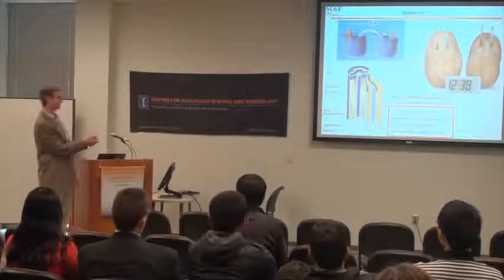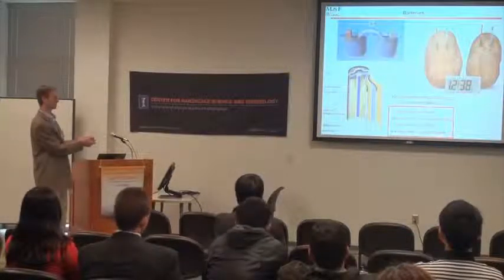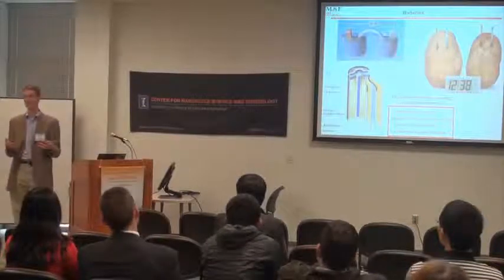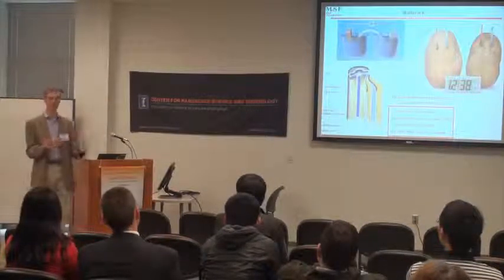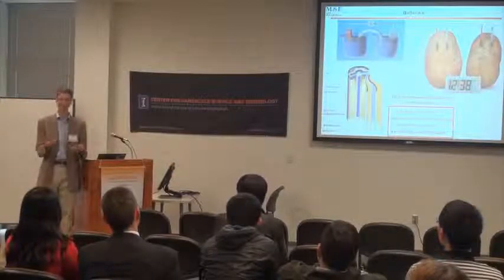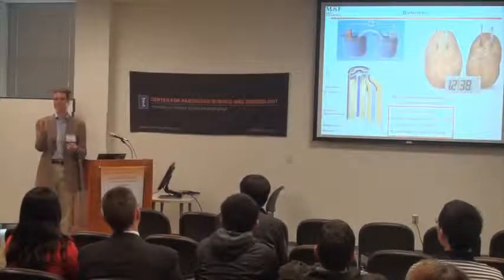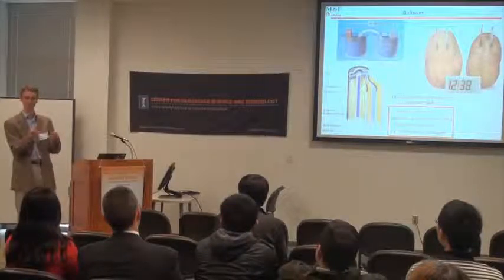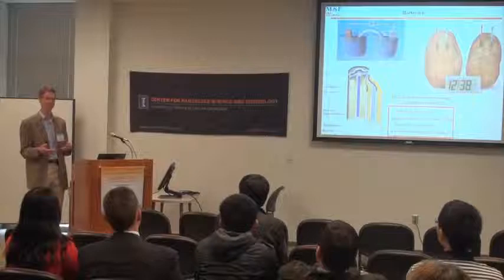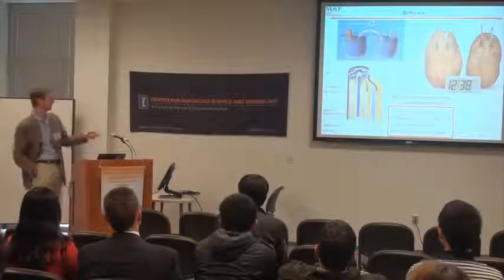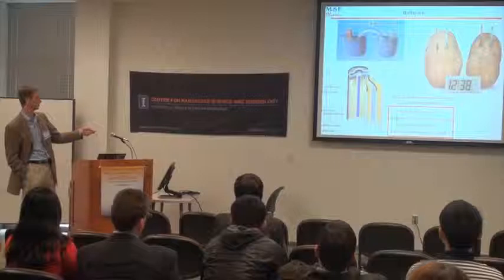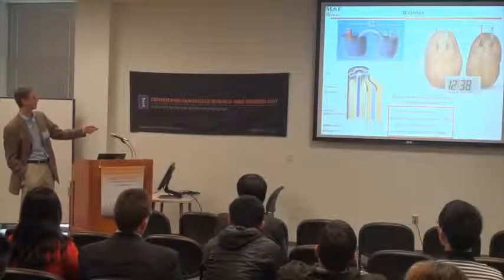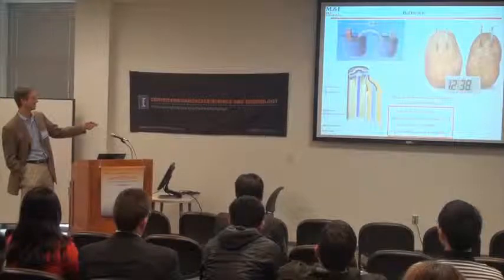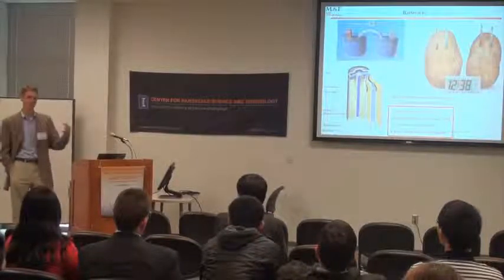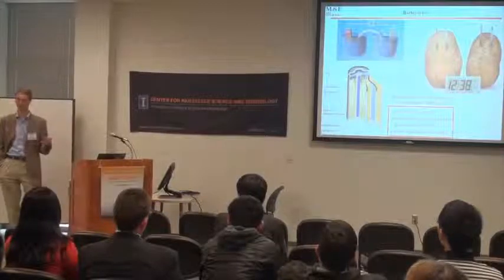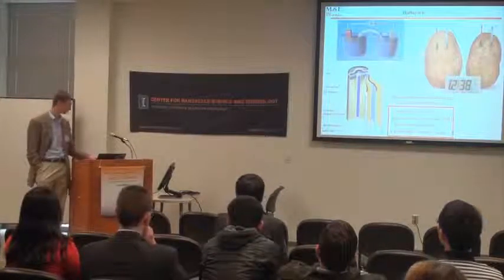That generates a large amount of heat. The electrolyte is almost always an organic liquid. You get a lot of heat, and it catches fire. And so this has been known to occur. It occurred in laptops a while ago due to manufacturing problems. Little metal shavings were present in the battery that would punch a hole through the separator. Boeing, of course, has had issues with the 787 and battery problems. And primarily that's because some sort of heat evolution leads to a failure mode here. But if you want to have high power and high density, high energy, you want a lot of this and a little bit of everything else. So you can start to see the challenge here. You'd prefer to get rid of the separator completely, but then of course your battery would short out.